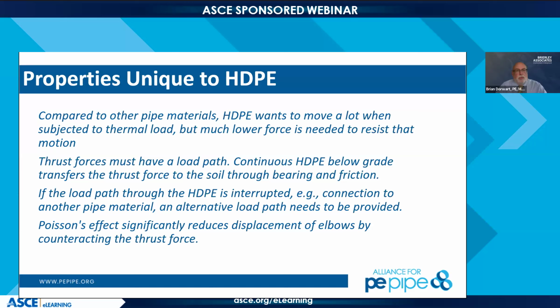Yeah, just to add to that a little bit, the thermal changes on short-term installations, like say trenchless installation, those you would use a higher modulus on. Whereas if your installation, say some pullbacks for directional drilling, might take 30 to 40 hours, you'd use a slightly lower modulus. And this information is heavily discussed in the PPI manual, and most manufacturers can tell you how much the modulus can change. So use the charts and figure out your time factor.